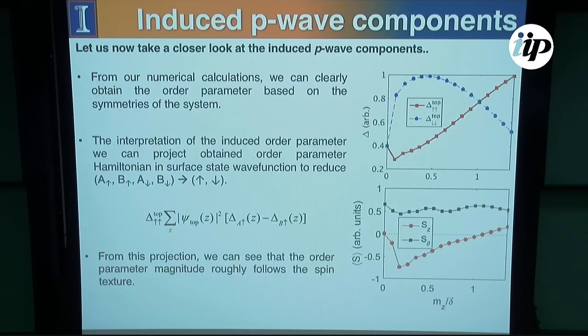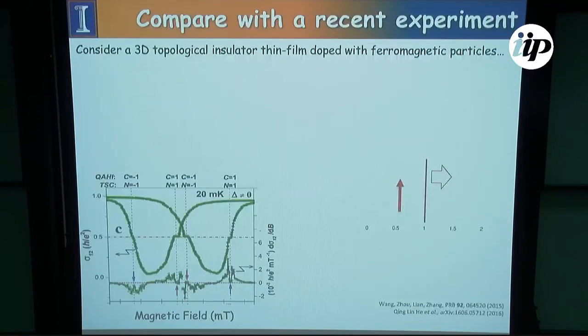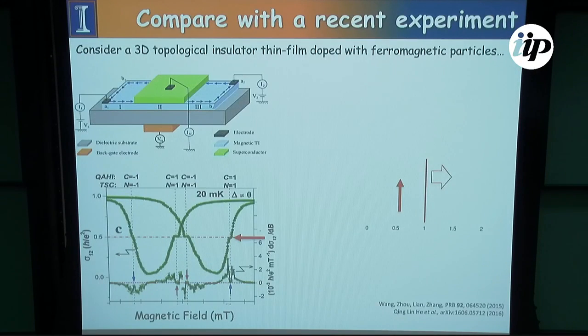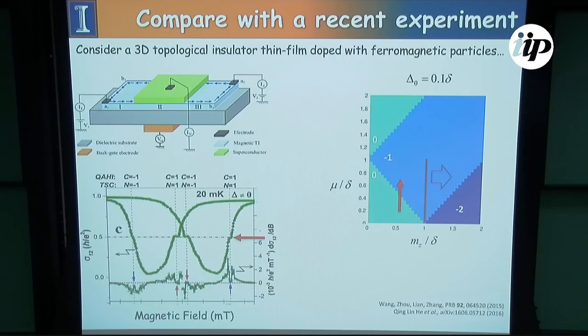So we can correlate this very nicely by projecting the full wave functions that we calculate from our complicated numerical calculations onto the surface, and we can in fact correlate nicely this out-of-plane canting with the amount of P wave that we should measure. That looks horrible, but this is a really neat and interesting experiment, and I think this is probably where I end.